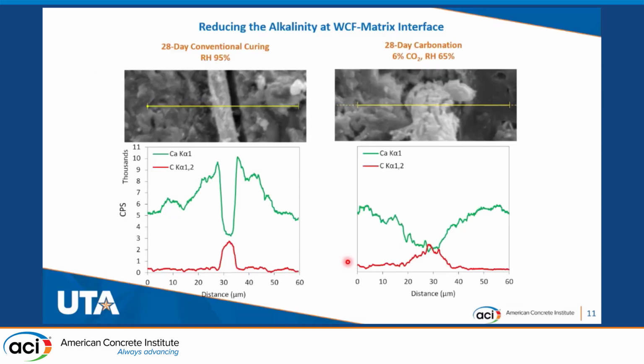But here, I'm first showing you results from SEM-EDS analysis of the waste cellulose fiber concrete, which is subjected to moist curing, conventional curing for 28 days. And the results are presented in the left part of the slide. We see from the EDS results a high calcium concentration on the fiber's outer surface, which is attracted by the negatively charged ions which are absorbed on the fiber's surface. The red peak here at around 29 microns is due to the carbon content of the fibers.